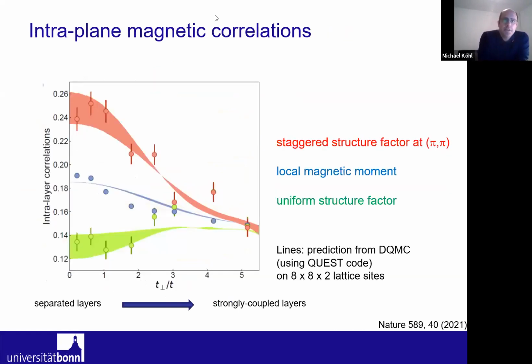Okay, so if we conduct this measurement as a function of the coupling strength, then we see the following. So the red data points, this is the measurement of the staggered magnetic structure factor at wave vector pi. So these are the antiferromagnetic correlations. And you see they have some dependence on the interaction parameter. And we compare this to some DQMC calculations, which we have done with some available code. And we see very good agreement. But the question is, where is actually our baseline for this experiment? So what do we compare to when we say we have antiferromagnetic correlations?